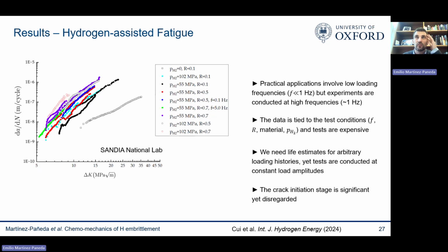The data is non-conservative, and it's also tied to the test conditions. Each of these points is useful for one frequency, one load ratio, one material, one hydrogen pressure. But of course, we want to be able to consider other conditions. Also, this is for a given load ratio, but realistic loading histories are much more complicated, and we cannot apply superposition since hydrogen brings a history dependency. We would also like to predict the nucleation of cracks.